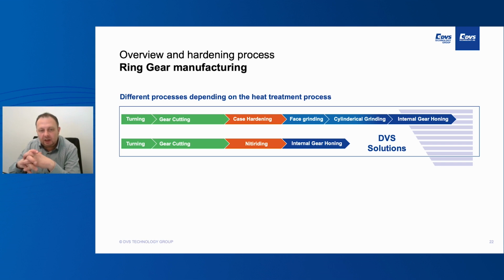And this is in the hardening process. One solution could be case hardening, another solution could be nitriding. In case of case hardening, face grinding and cylindrical grinding are necessary because case hardening has much higher distortions than nitriding. And finally, we have to finish the gear by gear honing. In case of nitriding as a hardening process, the distortion is much smaller, and it's not necessary to have face grinding and cylindrical grinding, and you can go through the internal gear honing.